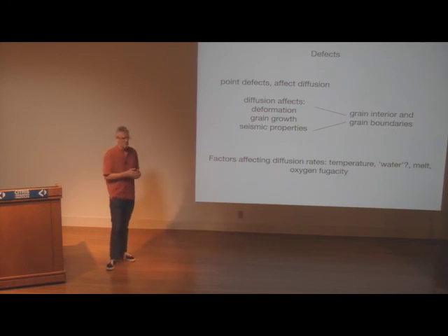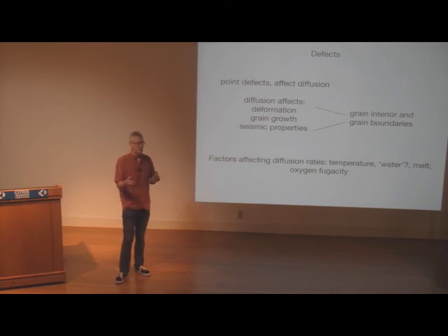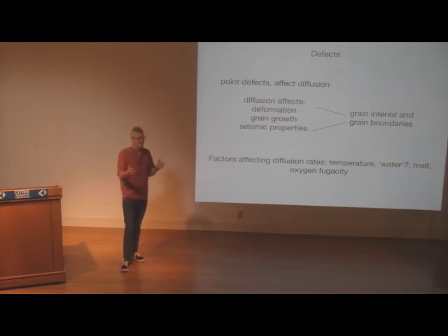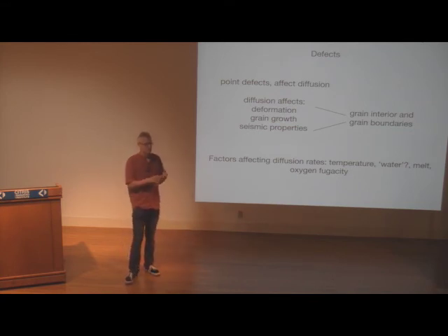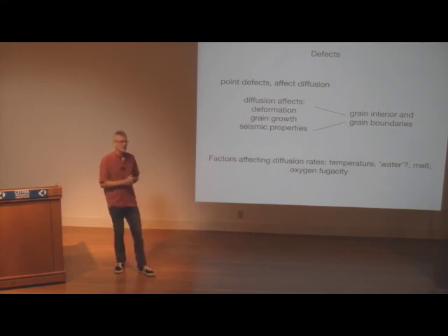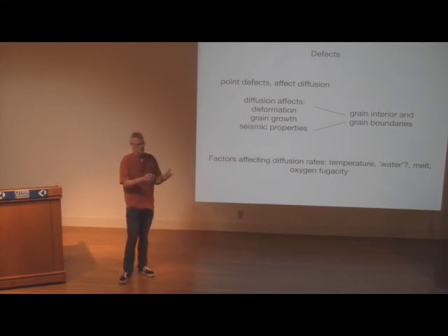For example, we've measured the grain size dependence of seismic properties. So you vary temperature, you can vary melt content and so on. You can also vary grain size and see which parameter range fits your seismic observations. And what we get is millimeter to centimeter, so it's consistent with the estimates that you get. Or you can do convection models and see, we have seismic anisotropy in the upper mantle.